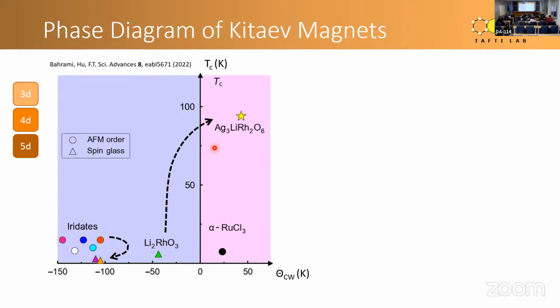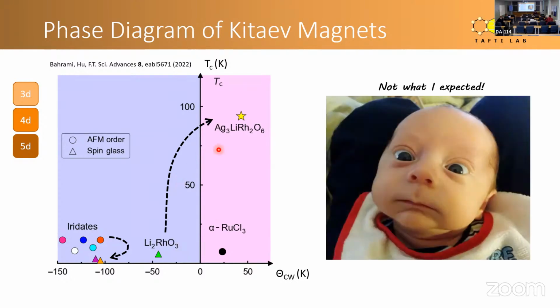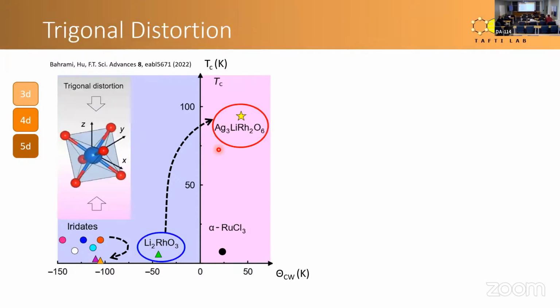When we did the exchange reaction, not only did the TC not go down, it went up by an order of magnitude. And this clearly was not what we expected. It completely went the opposite direction to what we predicted in the beginning. And that's the fun thing about doing research. Of course, when you predict something and it comes true, that's exciting. But sometimes when you predict something and it completely goes wrong, that's also very exciting, because it shows that you're going to learn something new. And we learned a lot in that experiment.